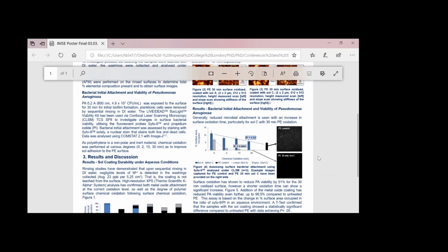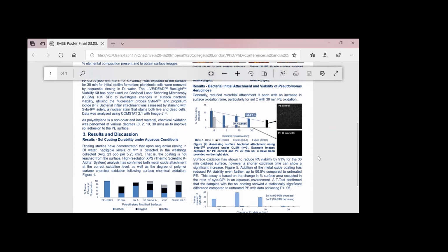Moving on to the bacterial assay results, the microscopy assay provides images, which I have analyzed using ComStat. This is a plugin for ImageJ to analyze the pixels into percentage area occupied after thresholding. What we can see is that the increase in oxidation pre-treatment times shows reduction in attachment, particularly for Sol C. I provided some example images where you can see that there's practically very little or no bacteria in this image compared to the control.